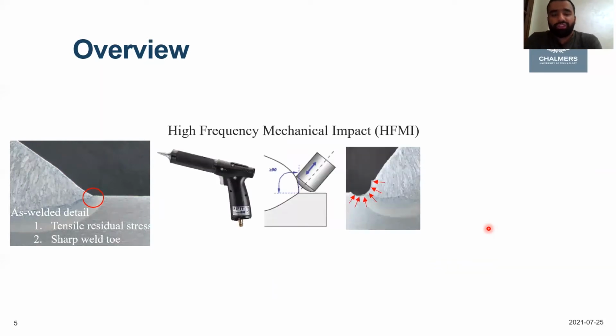You can use this small machine, which weighs less than 1 kilogram. It's easy to maintain, easy to operate, and of course, easy to handle. Any labor can use it, and it requires a very short time of training. And you're peening your structures with a very high frequency and creating this plastic deformation. This introduces compressive residual stress at the weld toe, which counteracts the effect of bad tensile welding residual stress. And it also reduces the sharpness of the weld toe with this small nice groove.